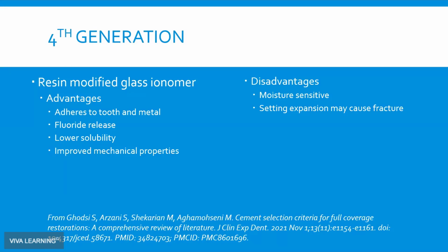You did have a significant improvement in mechanical properties due to the resin component. However, you had lower solubility, of course, but you still had the same kind of moisture sensitivity, because until the material set up, it was prone to dissolution. And if you read the actual instructions, I believe it was Fuji's instruction that you had to keep it dry for 14, 15, some pretty unrealistic length of time.